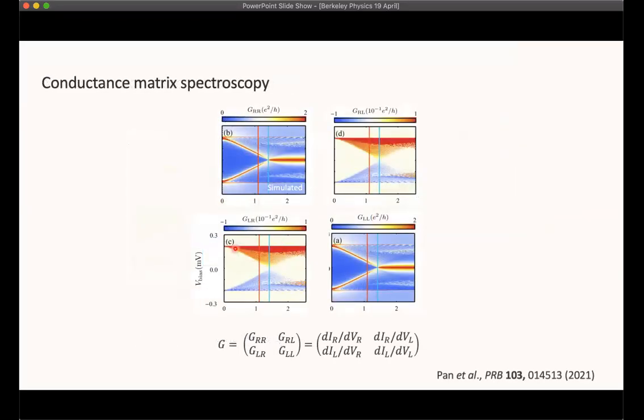Now with two junctions and two voltages and two currents, your conductance is now a 2x2 matrix. You have the change in current on each side with respect to the change in voltage on each side. And so these again are simulations, but they're showing you that we expect to see in local conductance on the diagonals a gap that closes, followed by the presence of some local zero energy feature on each side. And in non-local conductance, we also expect to see a gap that closes. So again, this is the gap spanning the entire wire, but no zero bias feature appearing in non-local conductance, because these Majorana quasiparticles are localized to ends of the wire.